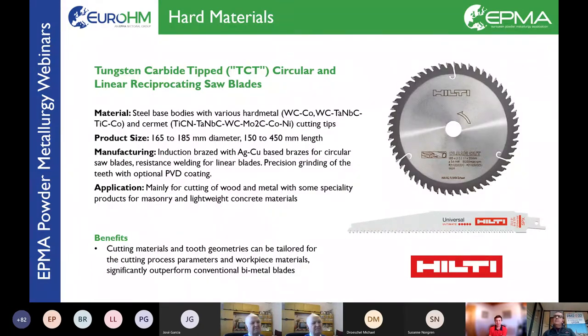The rotary circular saw blades are using the complicated tungsten carbide cubic phase materials, or even the cermets with cobalt nickel binders as an example, and other phases, carbonitride phases, and they are usually brazed on using standard silver copper brazes. And these have to withstand, of course, in handheld use, vibrations, impacts, high temperatures in continuous cutting, and they really are pushing the limits of the cemented carbides